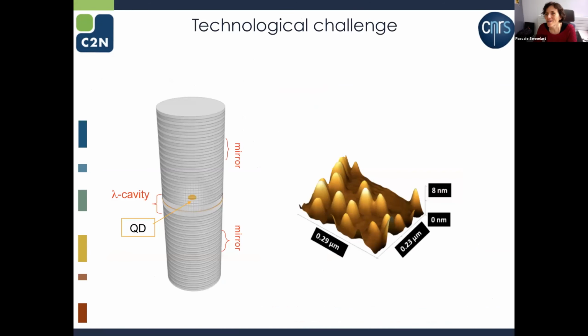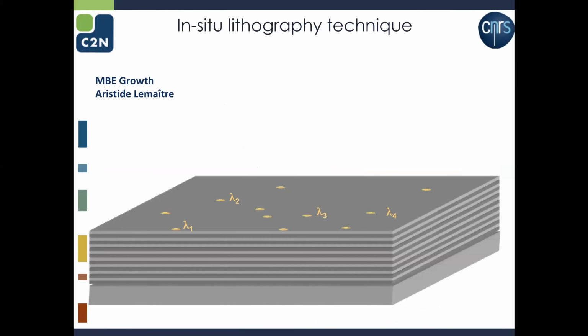Now it's not over. I want to put my atom at the center of the cavity. And this is, of course, a great challenge because you've understood from the way that the quantum dots are formed that we don't control their position. They have random position. So what we do is actually we have developed a technology that allows to solve this problem. We grow the mirror, with the Bragg mirrors, and then we grow the quantum dots. They have random position and random emission wavelength.